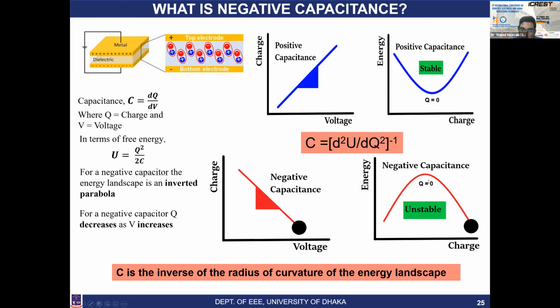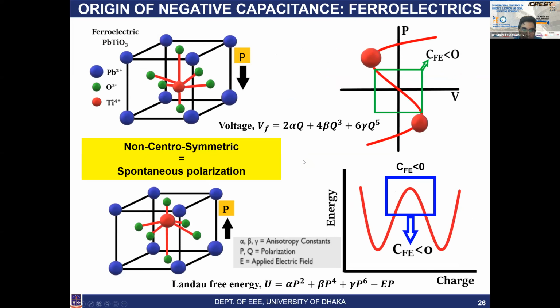And this is for the negative capacitance. But one of the problems with negative capacitance is the stability. Now, if you look at this, typically it's like a lead titanate crystal. The central atom is a little off-centered, which creates the polarizations. It could be either positive or negative polarizations, and then you can actually plot this energy landscape.